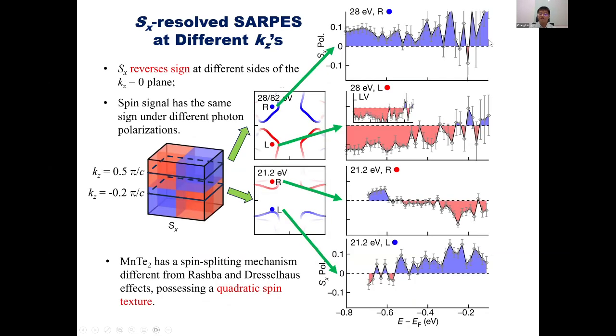So we actually did this at the beamline in Shanghai. This is also not a very easy measurement to do because a lot of those machines were broken at the same time back then. So we waited until about half a year later to do this measurement. This one is supposed to be blue here, and we measured it to be blue, and this one is supposed to be red, and we measured it to be red. So everything fits well.